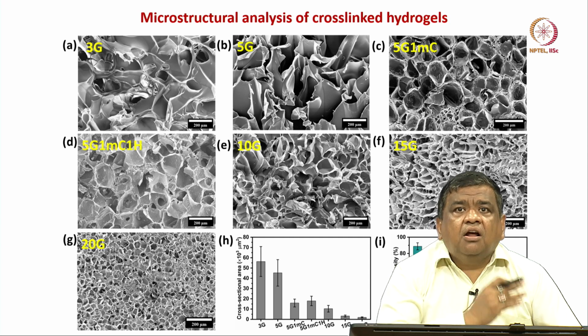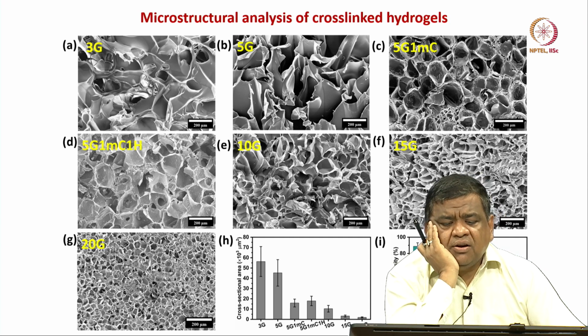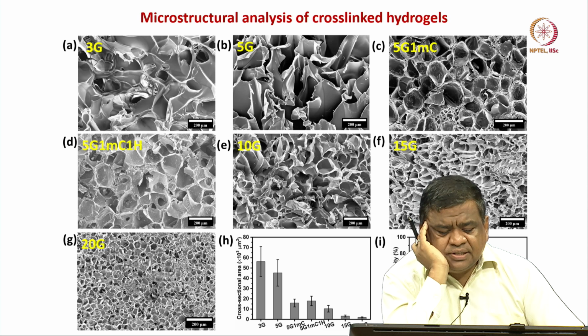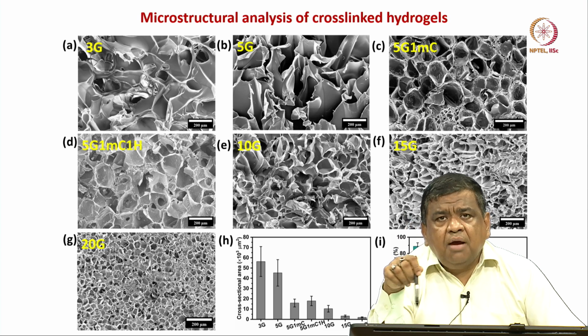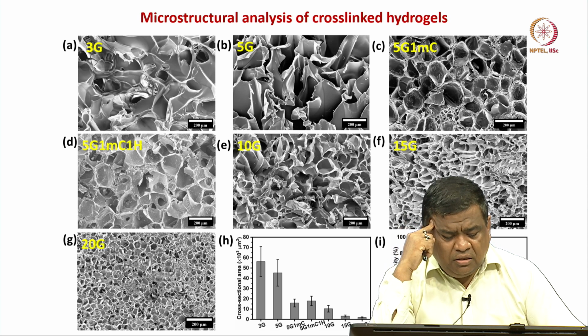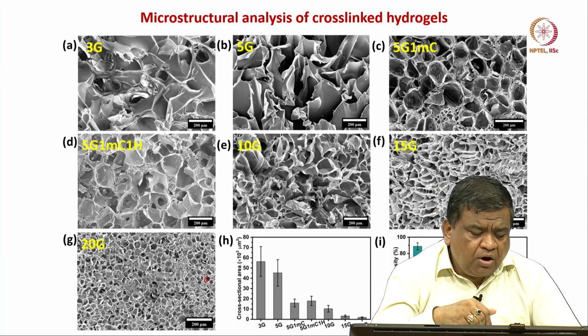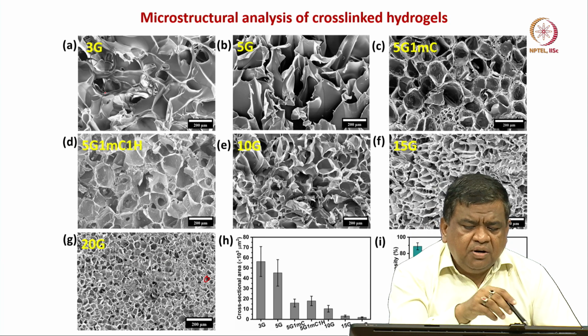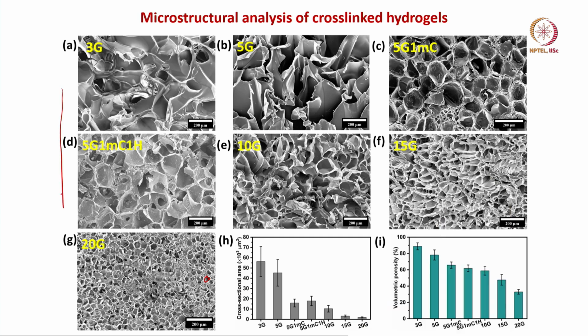The microstructure. Now, when you cross link, you will notice how the three dimensional pore architecture develops. If you go from 3% to 5 to 20%, the pore cross sectional area subsequently reduces, and volume percent porosity also reduces to around 30%. So, if you go from 3% GelMA to 20% GelMA.